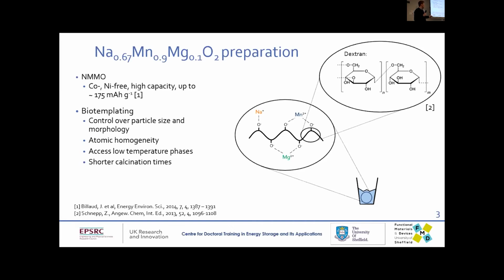It will coordinate, or the metals will coordinate to it, or it will coordinate to the metals, and then I dry it and then calcine it at a given temperature to generate our cathode structure. There's a couple of benefits this has over conventional solid state, chiefly that you have much shorter calcination time, so 2 hours versus solid state, which is about 20 hours. You also have this excellent atomic or ionic homogeneity because we've got this dissolution step, and you get very good control over particle size and morphology.